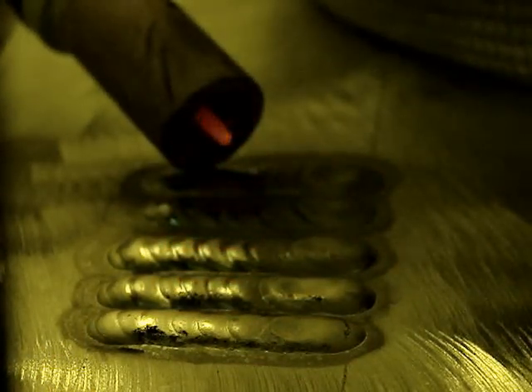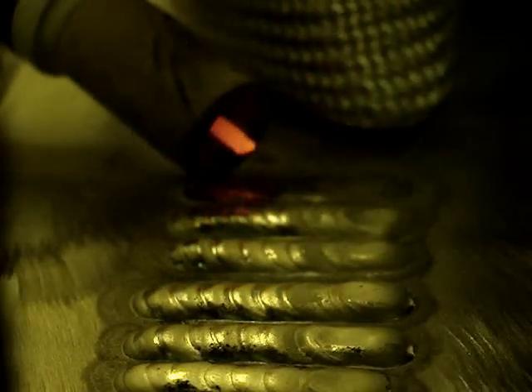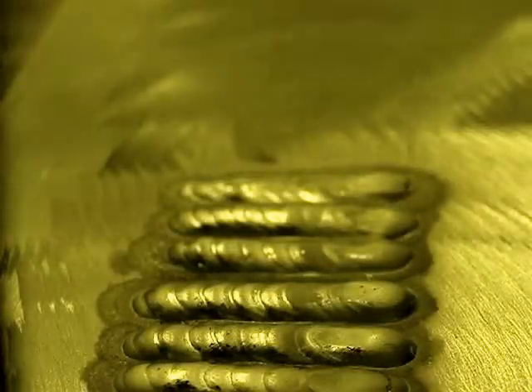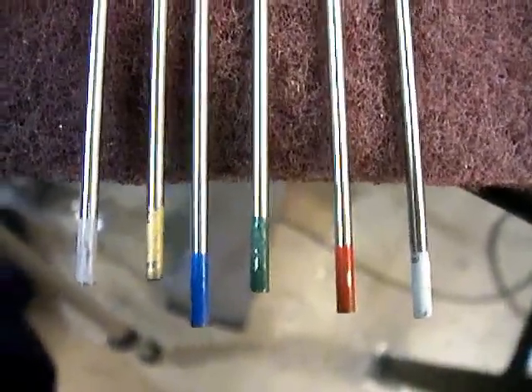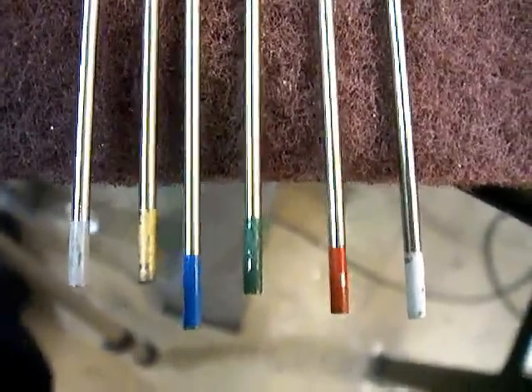Alright, after the pure, we went to the good old 2% thoriated, which they say will kill you because of all the radioactivity, as if all the rest of the stuff we weld isn't 10 times as bad for us. But, you know, I can't in good conscience recommend the 2% thoriated. All I can tell you is I still use it. But it does handle the current really well. And then last here, we used the 0.8% zirconiated, which did not handle the current very well at all and did not ball evenly either, and the arc wandered a lot.